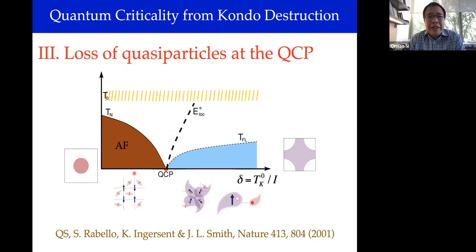And so this describes what happens going across the quantum critical point. At the quantum critical point, this pole strength approaches zero as one tunes the system from the paramagnetic side, and so the quasi-particles would be completely lost on the Fermi surface, and that has been probed in a number of ways.